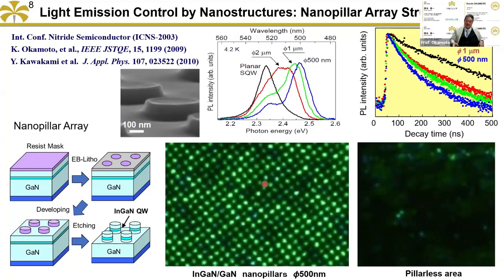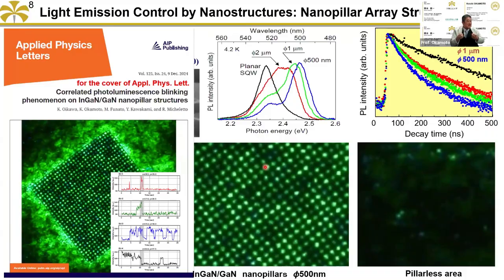Right? We found that when we fabricate the nanostructure, the two-dimensional quantum structure has a blinking like a single quantum dot. But that size is several hundred nanometers. It's much larger than a quantum dot, but still similar features are obtained. At that time, we couldn't understand what happened, but recently we found that this blinking is not random blinking. Some patterns are correlated, so it's synchronized. That's why it should have some quantum entanglement state or something like that, and it should be useful for some quantum devices. Recently we published this paper on the correlation, and that picture was the cover of the journal Applied Physics Letters.